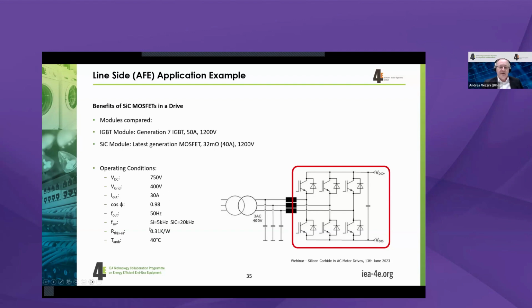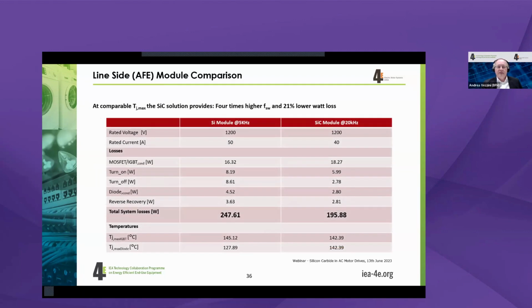In a silicon-based inverter, you would switch with 5 kilohertz, and with a silicon carbide, you would go up to 20 kilohertz. Remember what we saw before, increasing the switching frequency will not have such a big impact on the total losses of the silicon carbide. But now the impact, as you can see here, will be not so much in the total system losses. So as you can see, I'm operating silicon modules at 5 kilohertz with 247 total losses from the semiconductors, whereas the silicon carbide modules, which operate 4 times higher, are at 195. So you could even go a little bit higher with the switching frequency.